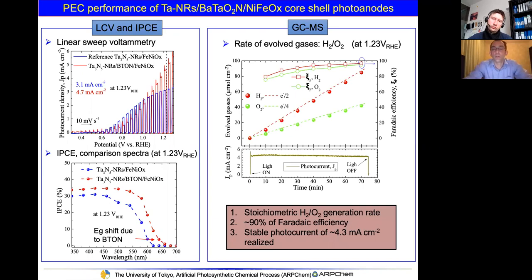And about the rate of evolved gases, its results are shown here. So we detected stoichiometric gas generation rate, 90% Faradaic efficiency, and very stable photocurrent of about 4.3 milliamp. Because this barium tantalum oxynitride material is much more stable than tantalum nitride. However, further optimization of the length and diameter of the nanorod, as well as the thickness of the barium tantalum oxynitride, is required. But this result just confirms the proof of principle of the proposed one-dimensional nanostructured material.